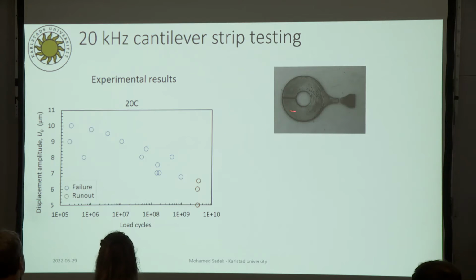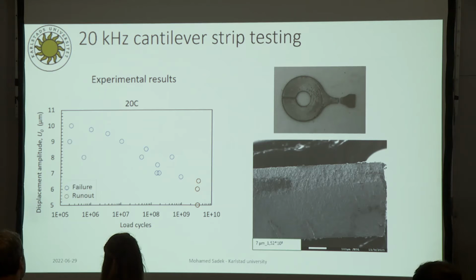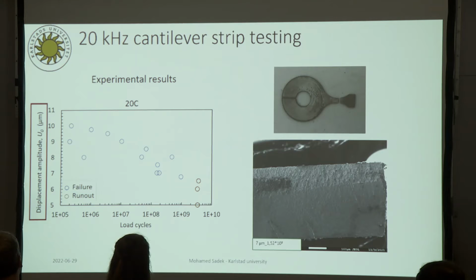We got correct fracture in the position where it is expected to fracture, in the middle of the waist. The fractography showed correct fatigue fracture as well, with evidence of plane bending and all the features that you would expect in a fatigue fracture. So it looks like it works perfectly. However, as some of you probably noticed, the S-N curve here doesn't include stresses, but rather displacements. That is because we don't know the stresses in this specimen yet. We are still trying to investigate that.